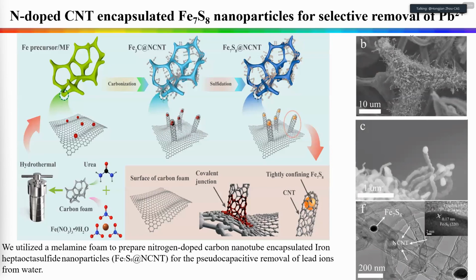And the third part, we try to develop the carbon combined with the pseudocapacitive electrode. As we know, for the pseudocapacitive electrode, most people worry about the stability. So we try using carbon nanotubes to encapsulate our material to enhance the stability. We utilize melamine foam to prepare nitrogen-doped carbon nanotube encapsulated iron heptasulfide (Fe7S8) nanoparticles for the pseudocapacitive removal of lead ions from water.